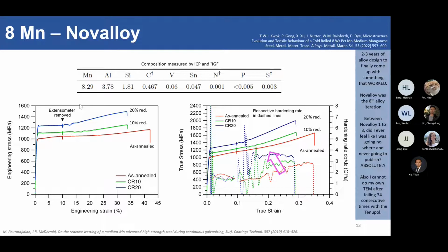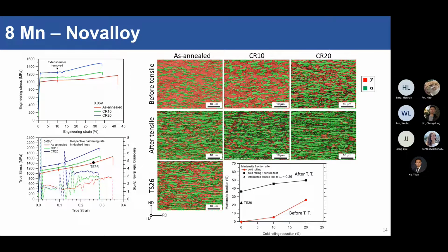What that means is that we are changing the hardening behavior of these steels, and I really wanted to know why. So we looked at these steels with EBSD again, my favorite technique, red and green. We look at it before and after your tensile testing. And what we've noticed is that with cold rolling, we've increased the martensite fraction of this steel. So when we cold roll it, we activate the TRIP effect already. But what is interesting is that when we do a tensile test after that, the final martensite fraction also increases. So we didn't change the composition, we didn't change grain size, we didn't change anything, but the cold rolling somehow was able to improve the martensite transformation ratio in these steels.